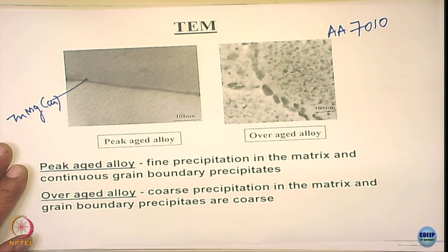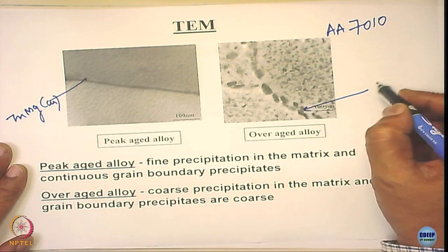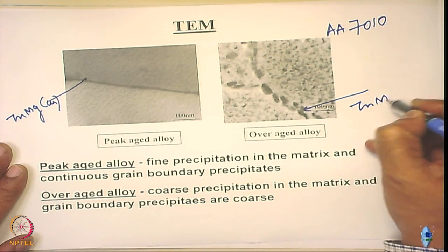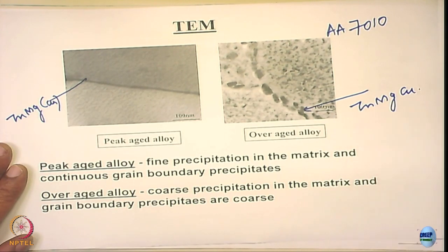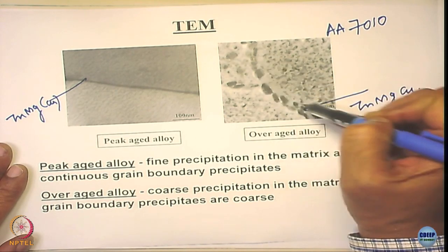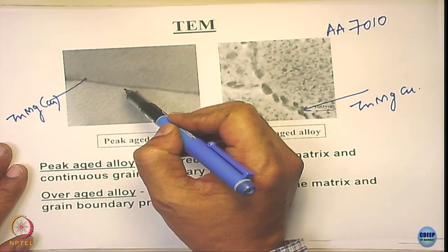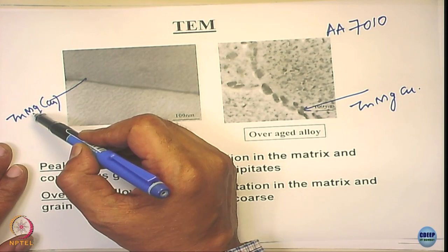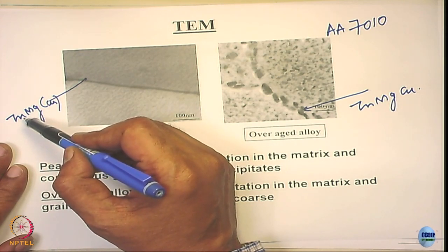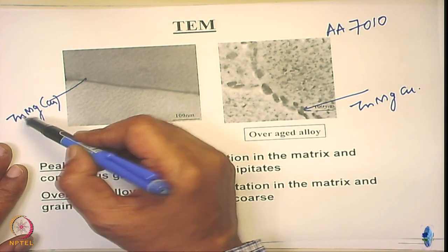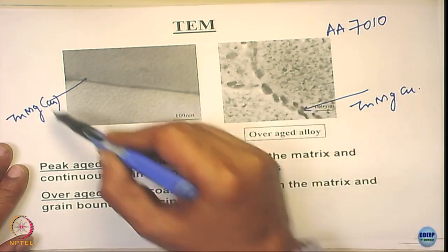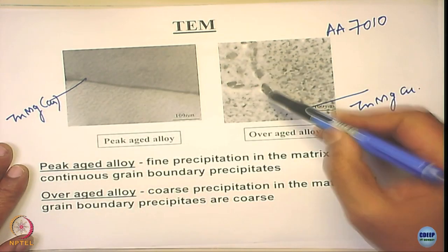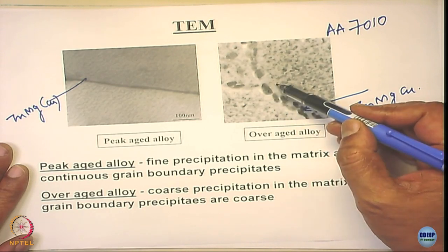And they are almost all equilibrium precipitates. Over here, it again has zinc, magnesium, and quite a large amount of copper, okay. So, the precipitates become relatively noble here as compared to this. Why? You take aluminum and compare that to magnesium, magnesium is active. In fact, even zinc is active, because zinc does not form a passivation. When you add copper to it, the precipitate becomes noble. So, they become noble precipitates with respect to the matrix.